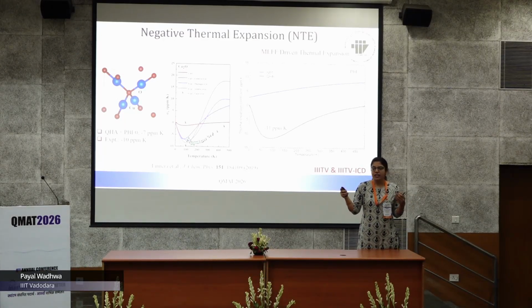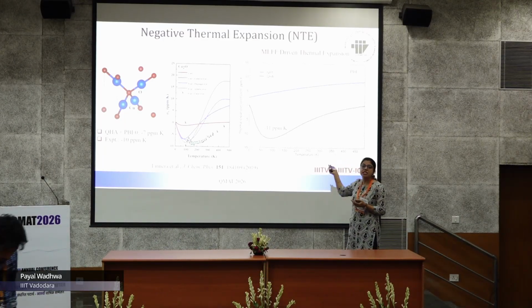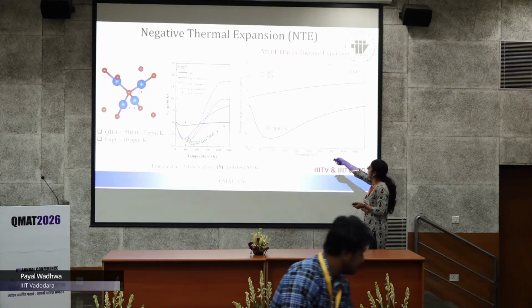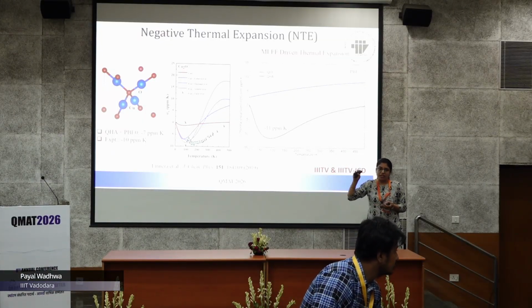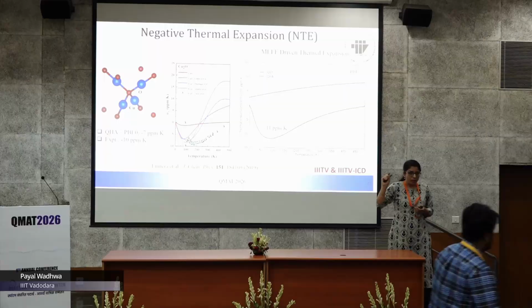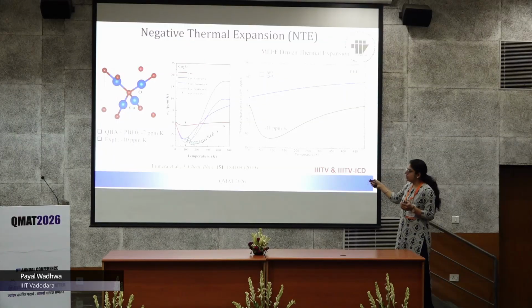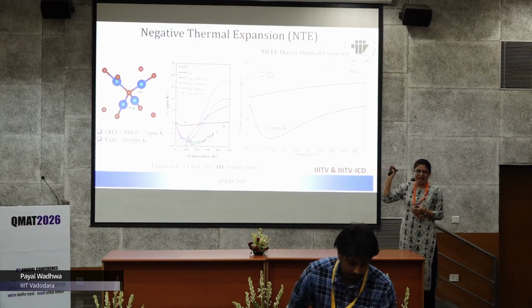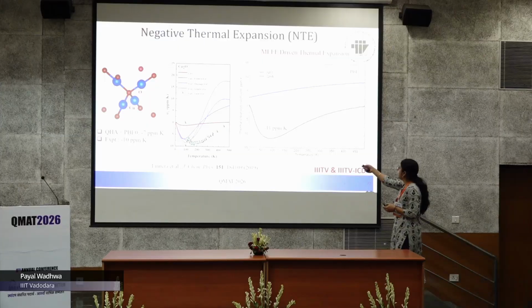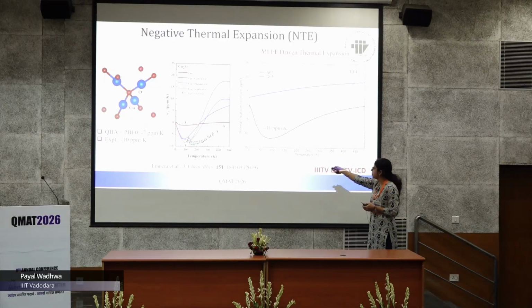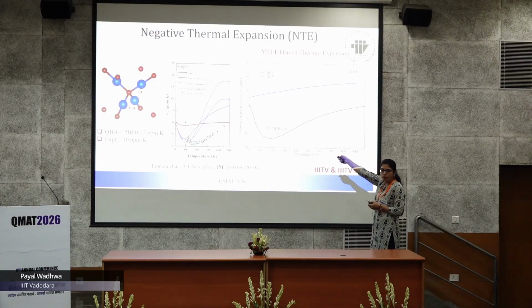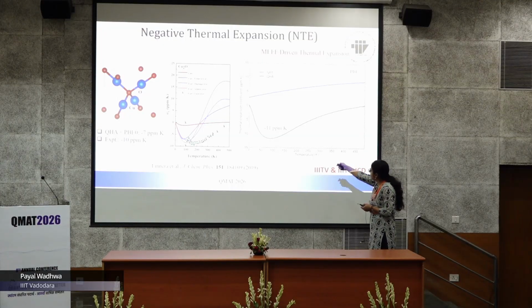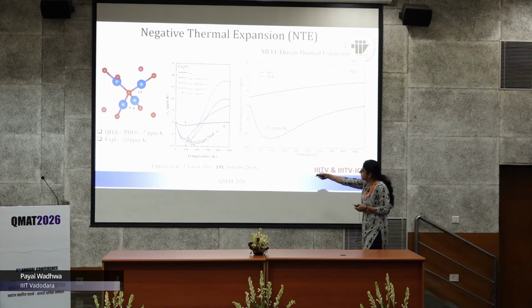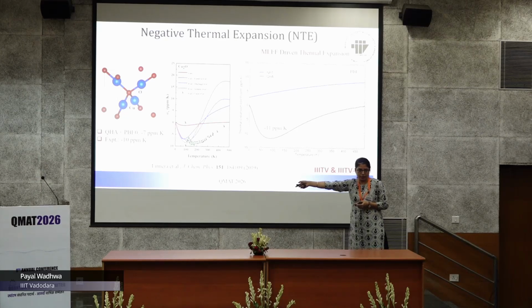Once the force field is ready, we perform the NPT simulations driven by force fields. As I already mentioned in the first slide, MD fails at low temperatures, so NPT couldn't capture this negative thermal expansion. But when we perform this QHA with PBE, we found this negative thermal expansion, and we can see here that this value is minus 11, which is in good agreement with the experimental reports.